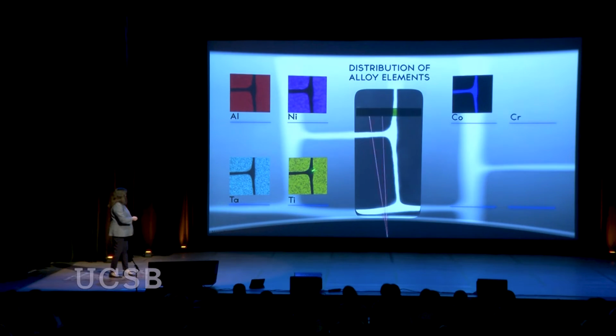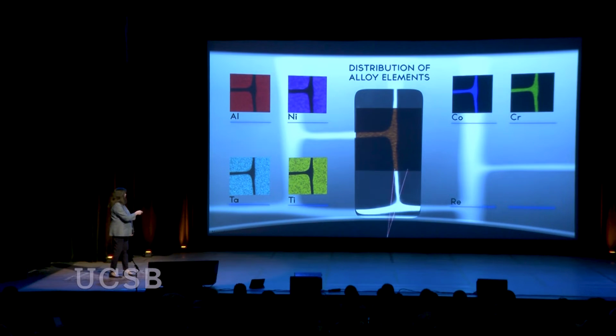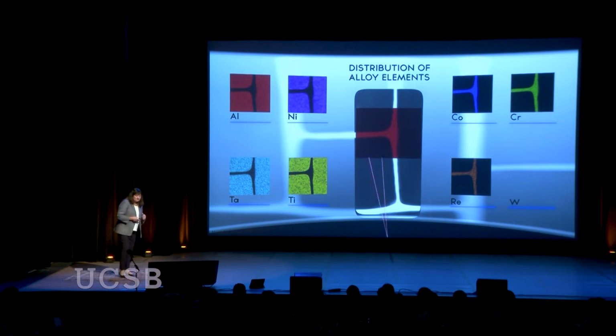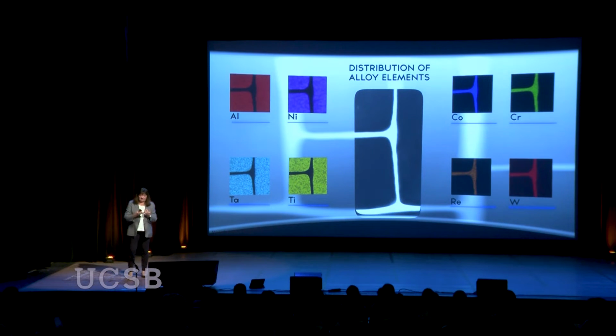Now, earlier I said we need alloys, and what we really are doing is mixing together a lot of elements, but we have to figure out which of the phases the elements go to. And so everything shown brightly here sits in the blocks, which we would call precipitates. And then the cobalt, chrome, rhenium, all of those things sit in the mortar, if you will, that hold the blocks together. And so the point is we have a lot of length scales.